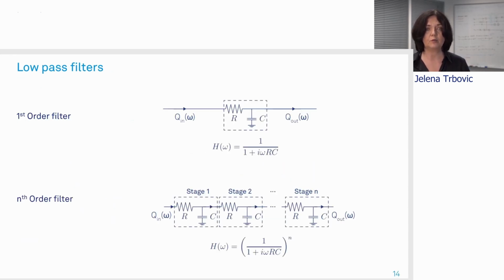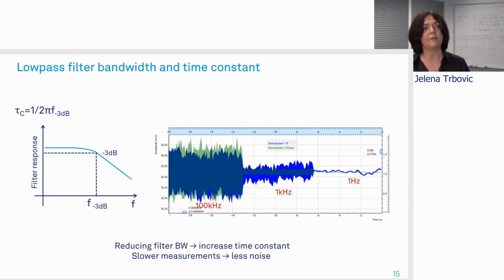And what's also important to know is that the low pass filters need to be set carefully. You can start off with the first order filter. It's an RC type of filter, and then you can stack a couple of additional filters on top of that if you're not happy as to how much noise your system is admitting. So you create a low pass filter for your system. And you do this in a lock-in amplifier by choosing the appropriate time constant, which is inversely proportional to the bandwidth of the filter, which signifies the frequency where half of the signal power is admitted through the filter. So you can see here that if we increase the bandwidth of the filter, we have lots of noise admitted.